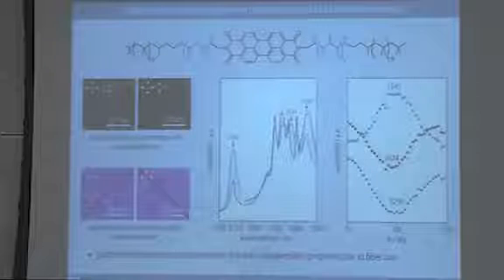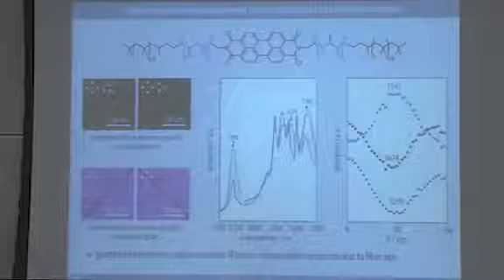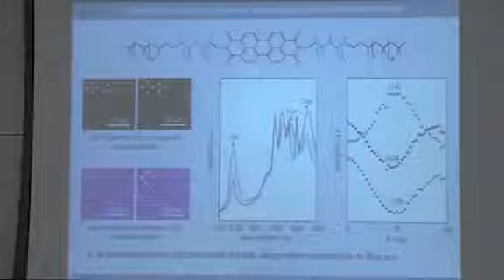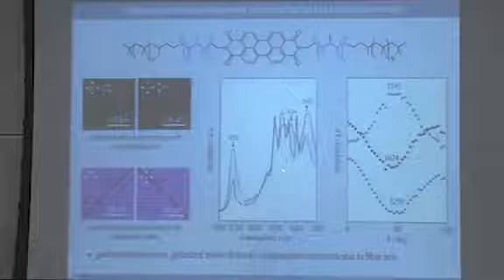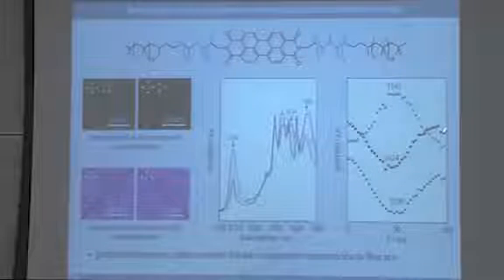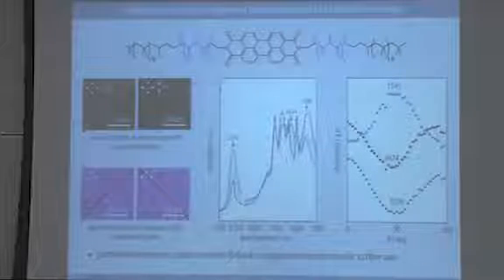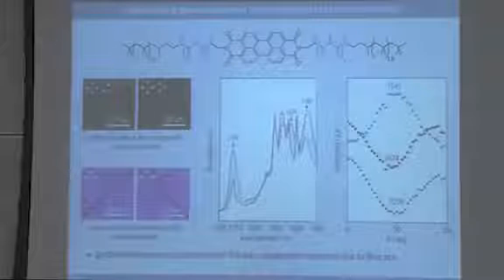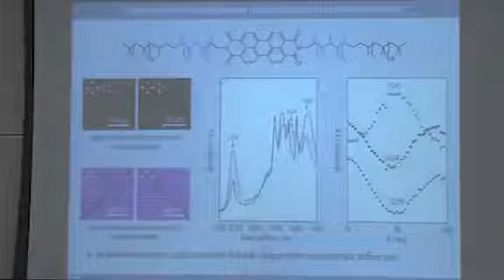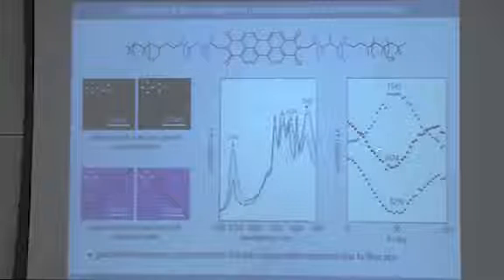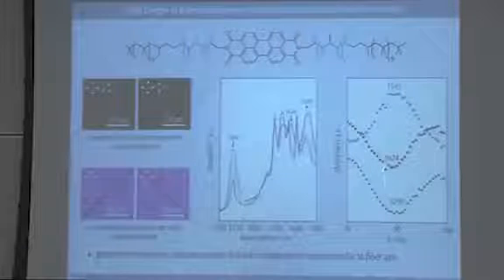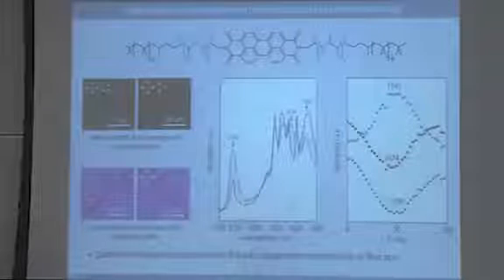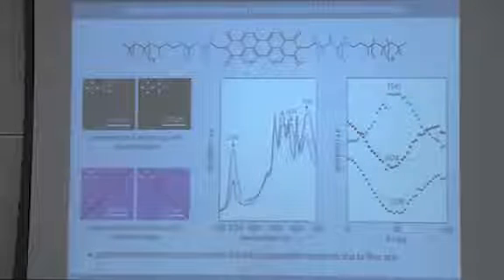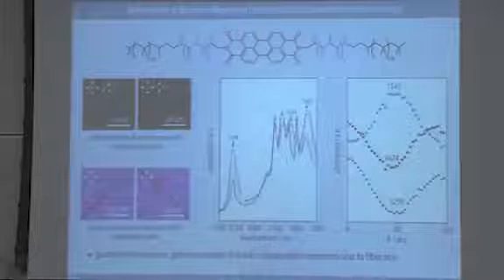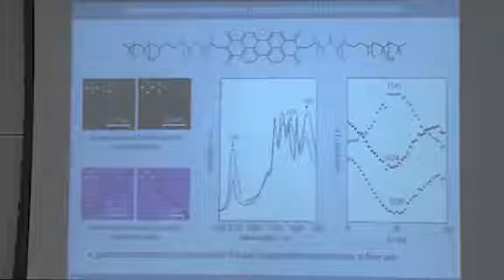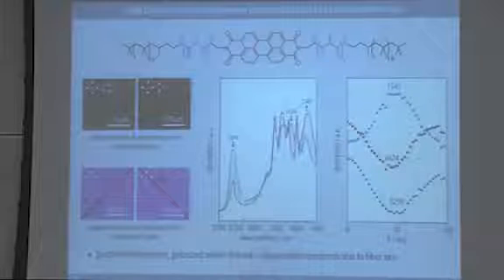And accordingly, polarized IR microscopy shown here for the amide-2 band, the amide-1 band that I already referred to earlier, so the CO stretching vibration and the NH stretching vibration, shows a systematic variation depending on the angle of the polarizers of the IR microscope. And again, this tells you that because the CO stretching vibration is smallest in 90-degree position, the carbonyl groups are again parallel to the fiber direction. The oligopeptides are thus perpendicular to it. I'll come back to that in a second.